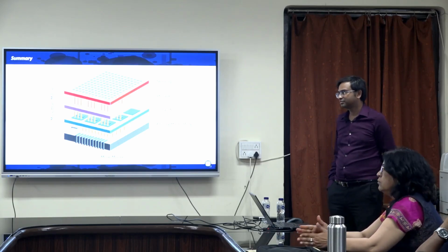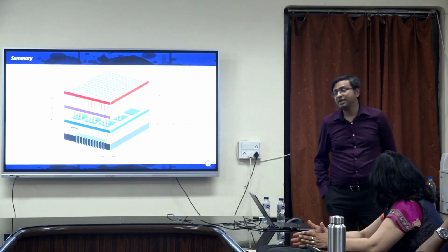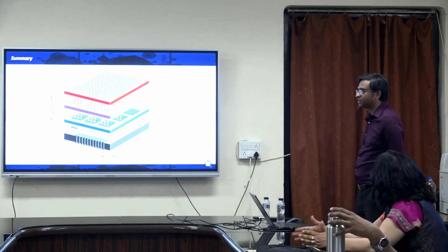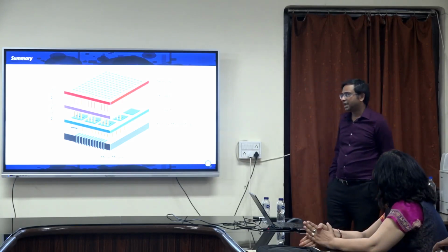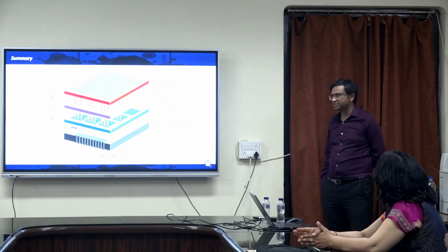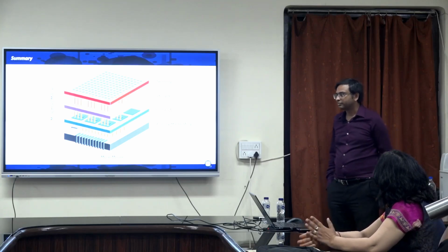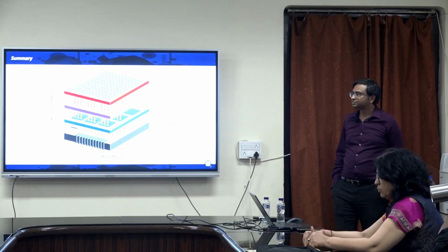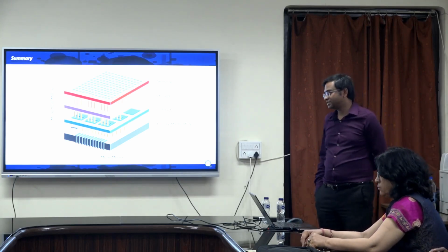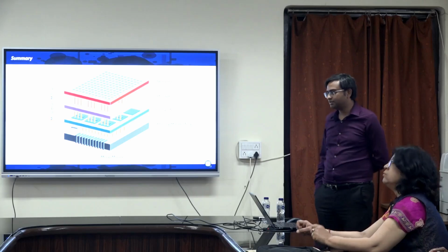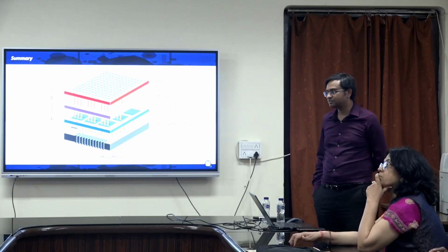So what precursors do you use, for the metal? We are using molybdenum hexacarbonyl, Mo(CO)6, for the molybdenum precursor. For sulfur, we are using H2S. For selenium, we are using H2Se. Does that mean everything is optimized, the flow rate, everything? We are still optimizing, because we still want to improve the quality of the material. These materials still have a lot of defects.